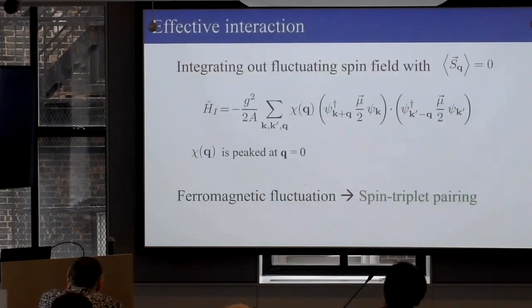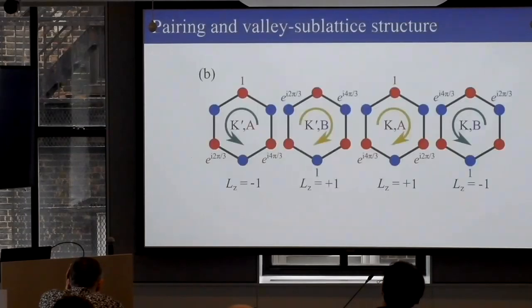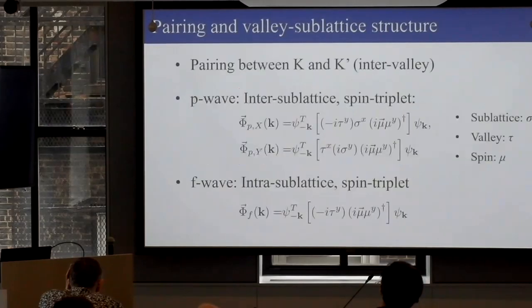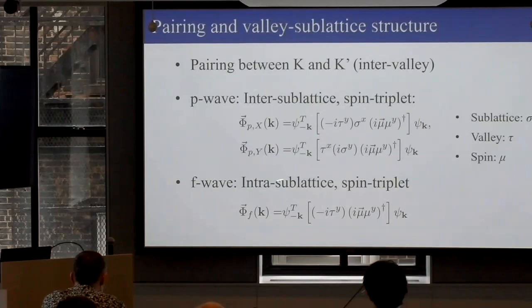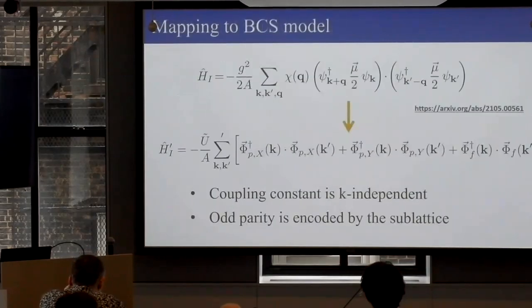And then you do the same calculation that I was telling you about with this spin triplet, with this ferromagnetic fluctuation. And we can take into account the symmetry, including spin fluctuation bosonic component easily, because you've already done it for phonons. And then we can identify which valleys are pairing, what should be the symmetries, P and F wave, because you can have intersublattice, intrasublattice, both are spin triplet. It's a bit dizzying.